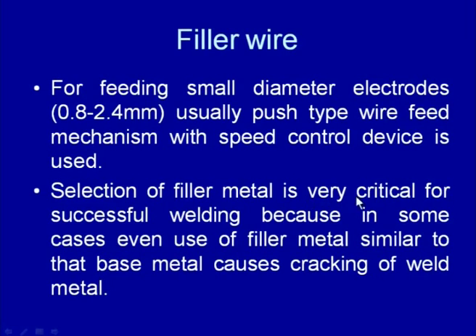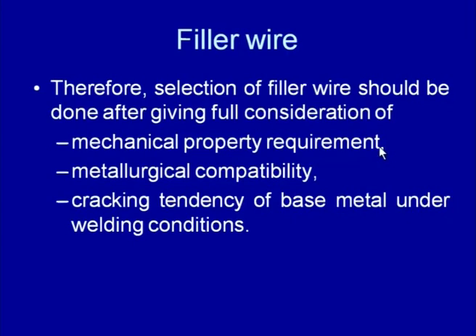So, the selection of the filler material is very crucial for successful welding, because in some cases even use of a filler material similar to that of the base material also causes cracking of the weld material. Therefore, the selection of the filler wire should be done after giving full consideration to the mechanical property requirements. We should select the filler material such that it is able to offer properties that fulfill the functional requirement of the weld joint, which may be in terms of hardness, tensile strength or fatigue performance.